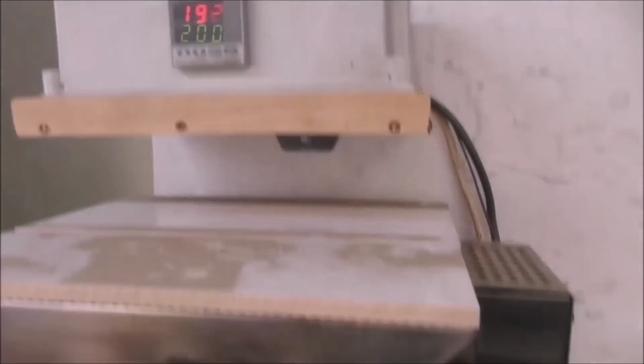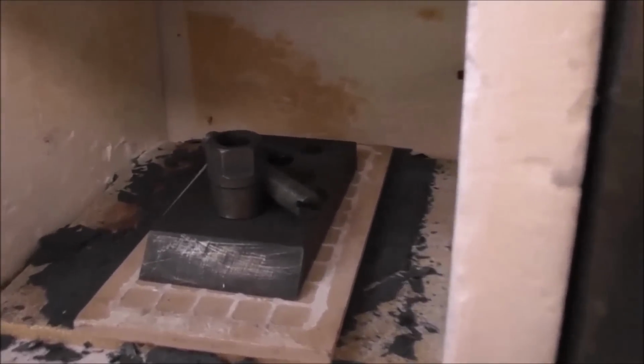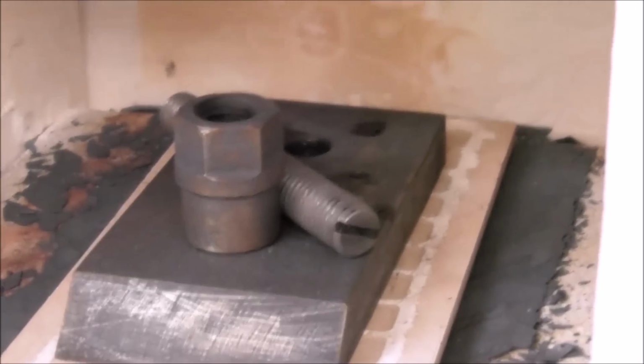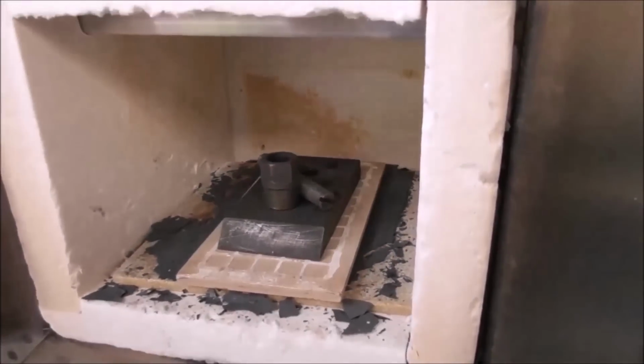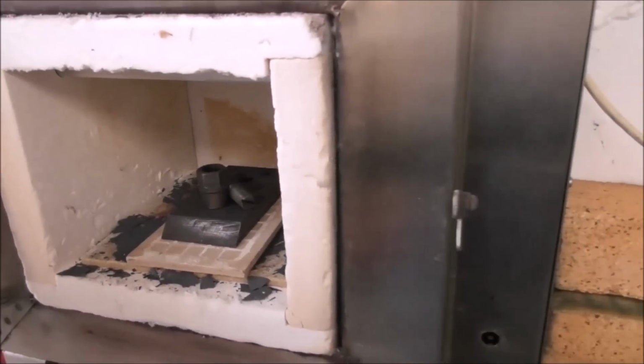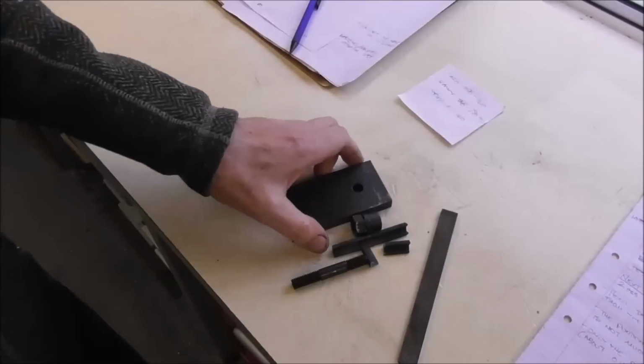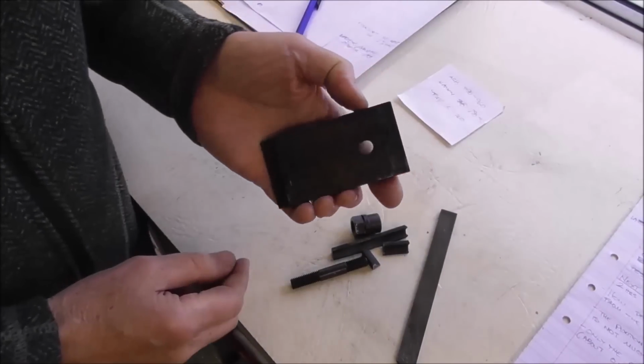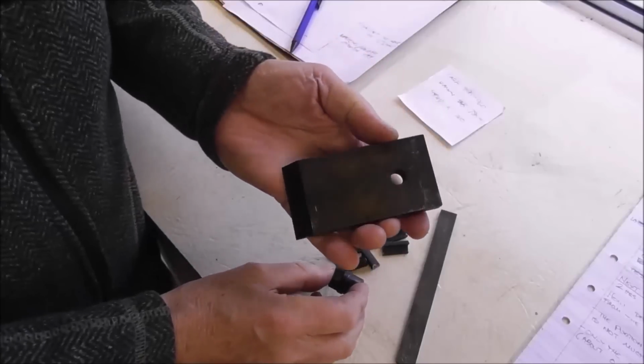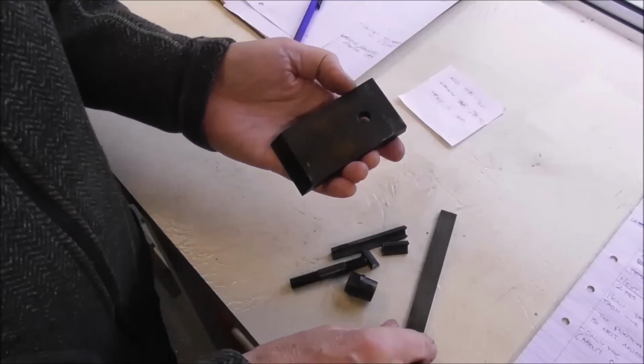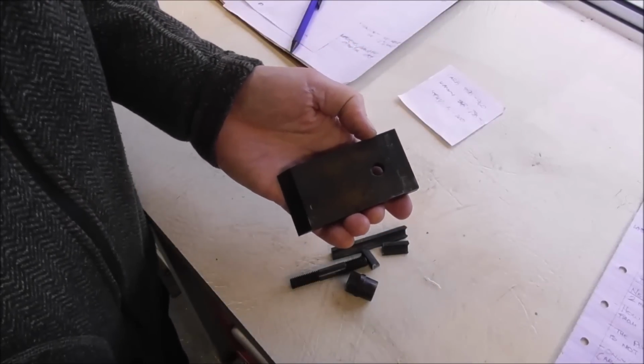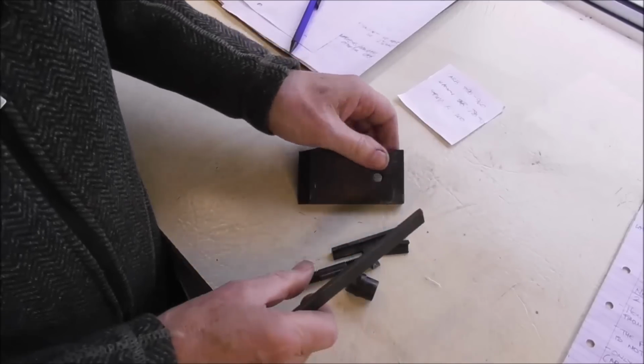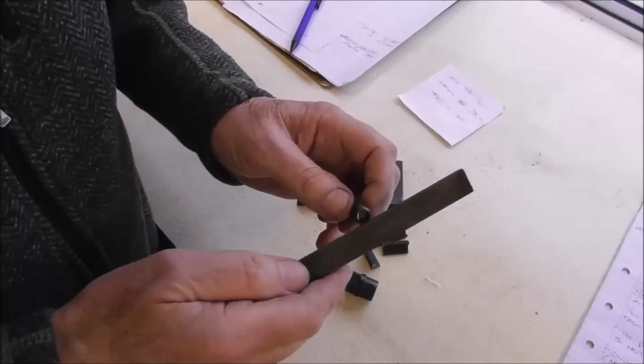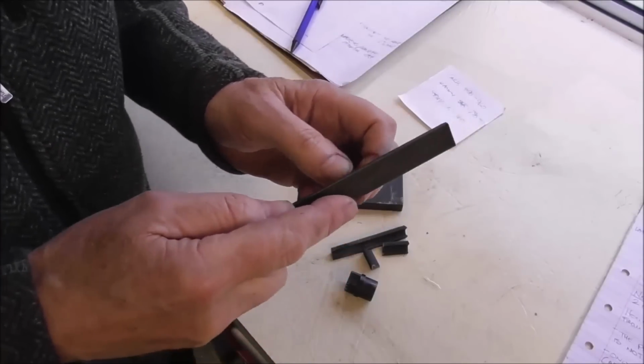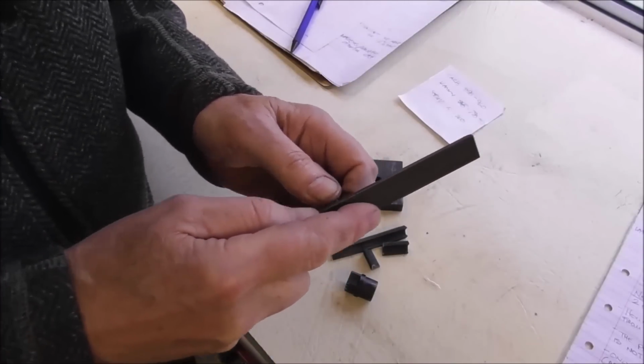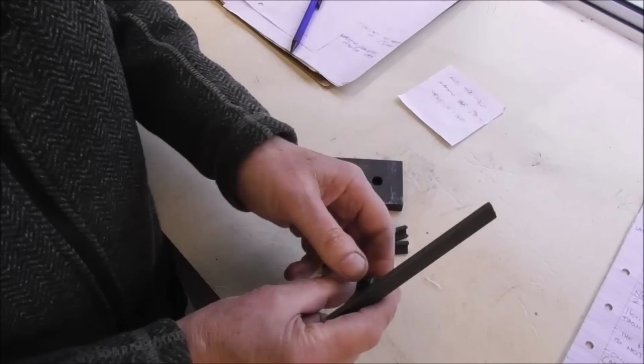So I'm tempering these parts at 200 degrees C. You can see there they're just going brown in color. That should be relieving stresses without softening too much. Well, those parts are tempered now. You can see they're sort of brown in color. That's an hour or so at 200 degrees C, and most of the parts are still really hard, you know, about file hardness, around 60 Rockwell C.